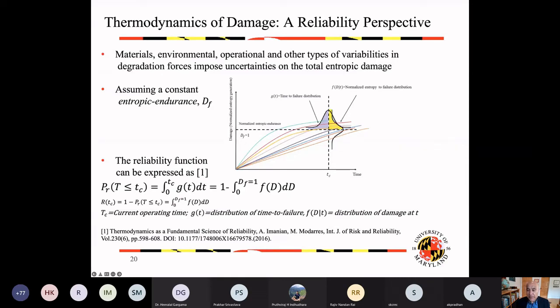And I would then argue that this probability in the orange should be equal to the probability of the time of failure to the left of this line. If you look at this blue area to the left of the line, then of course that should be equal to this orange area, because that distribution, based on the definition in reliability, is also the probability of failure by this time. So I find the probability of failure through dissipation, and I find the same equivalent through the time of failure distribution, which is the traditional reliability models. Therefore, I can correlate these together.